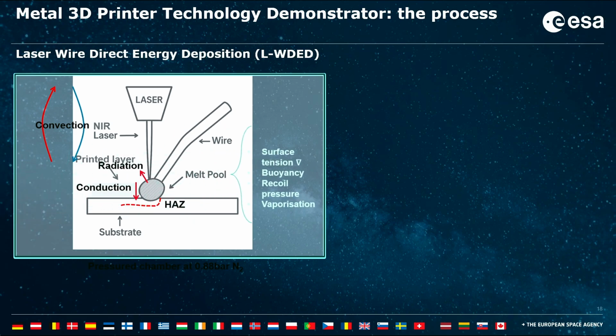And you have a certain number of other physical phenomena. You have the surface tension, which determines the shape of your melt pool. And it's quite important because the shape will determine as well the quality of the layers. You have buoyancy. You have recoil, which is the effect of the laser on the melt pool itself. And vaporization, because you are working at quite a high temperature.